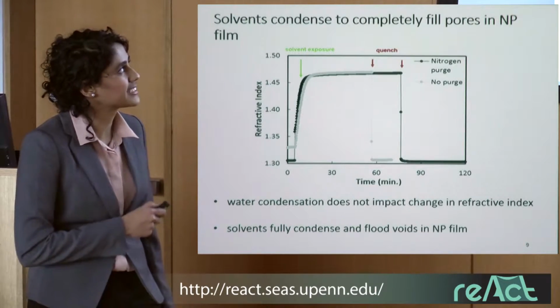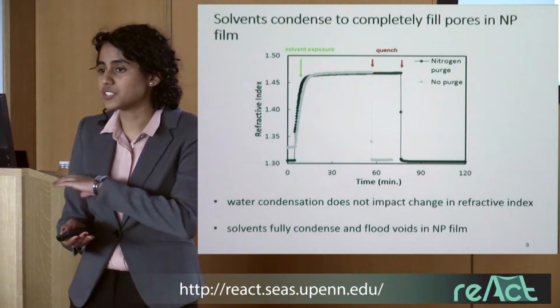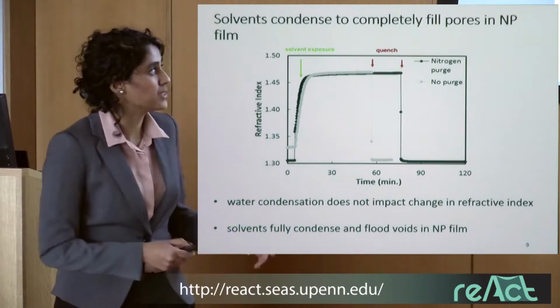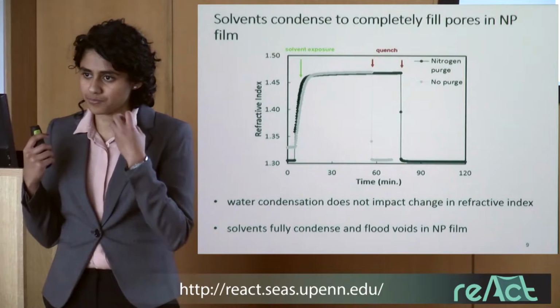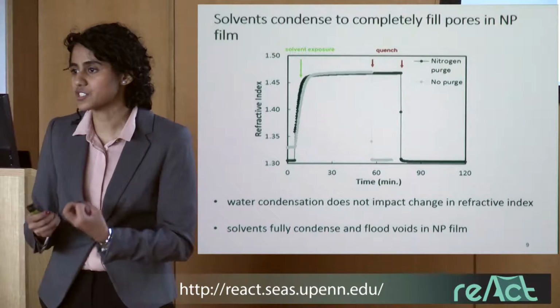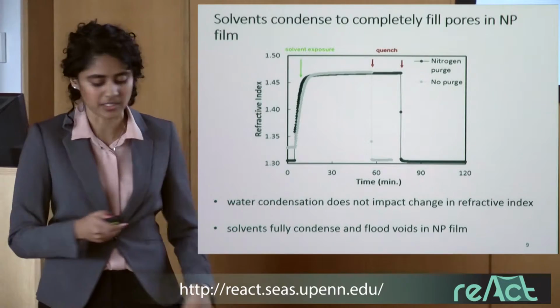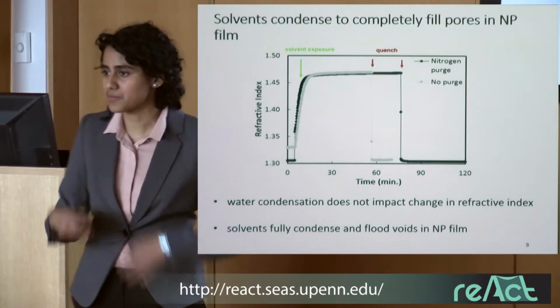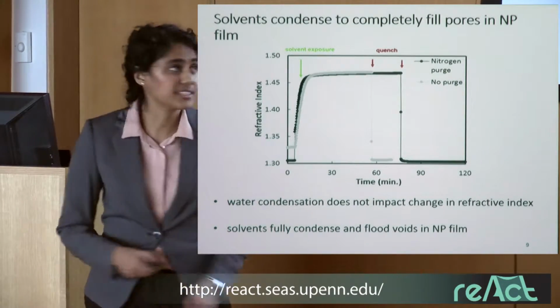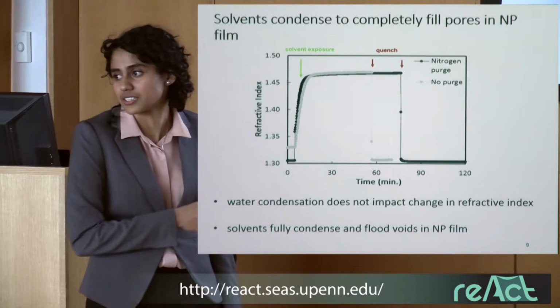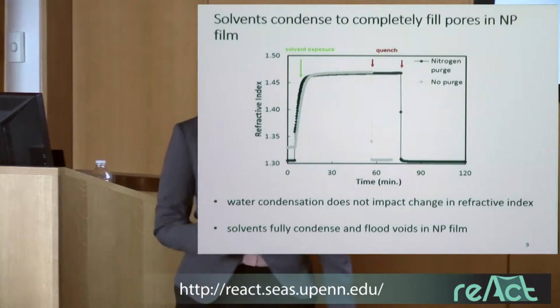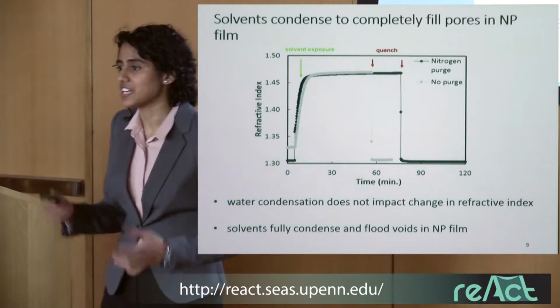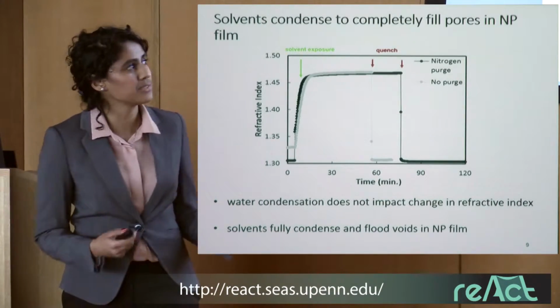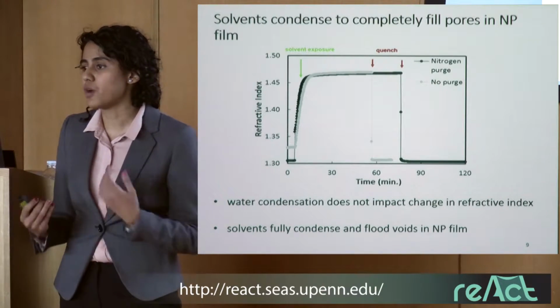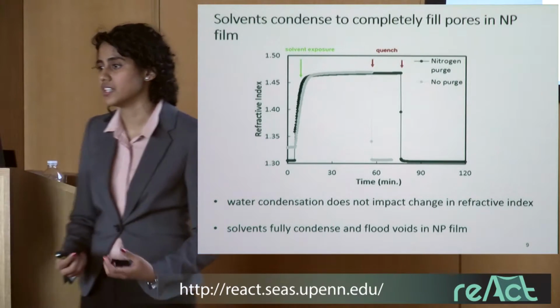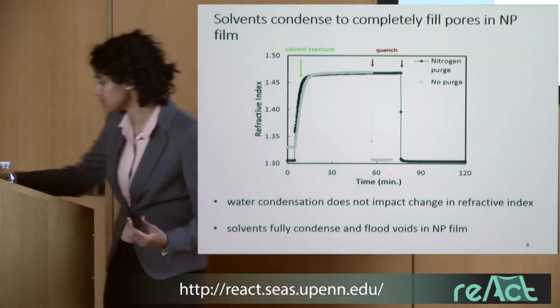And this refractive index change actually indicates that my film is fully flooded with solvent. So my nanoparticles are small enough that I can actually induce full flooding of my nanoparticle layer with solvent. And when I quench the system, basically by again purging it with nitrogen, I find that it reversibly goes back to the original refractive index. And this is a sanity check in that any irreversible change I observe in the bilayer system is probably due to polymer infiltrating and not just remnant solvent or other things condensing in my nanoparticles.